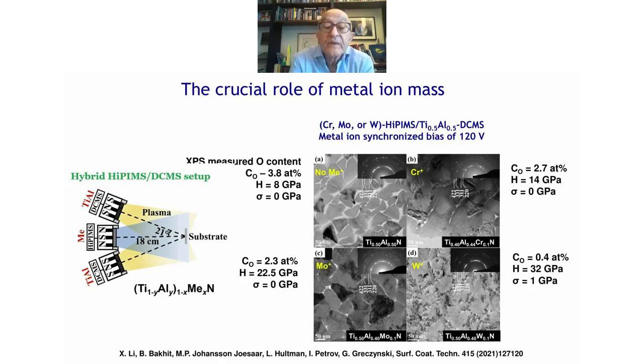Chromium, moly, and tungsten. So in the upper left plan view TEM, you see huge porosity, which kind of disappears when we go to the heaviest metal. Now we quantify the porosity by measuring by XPS the oxygen content in the films, which is noted here in the upper left corner. And for the open DC sputter film, this is 3.8%, very low hardness, low stress.